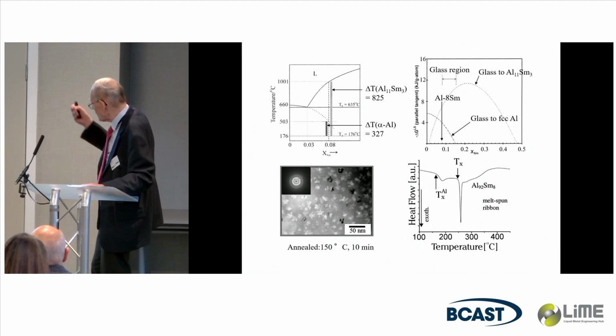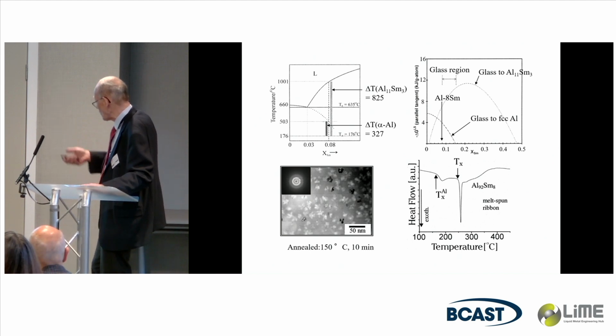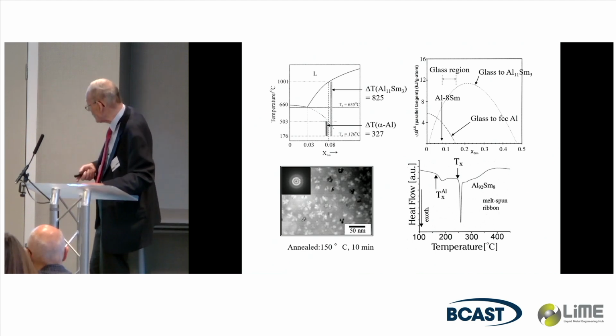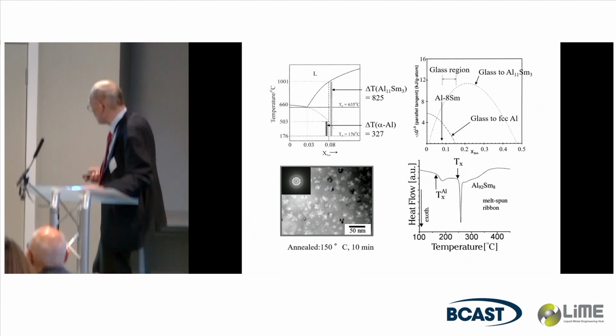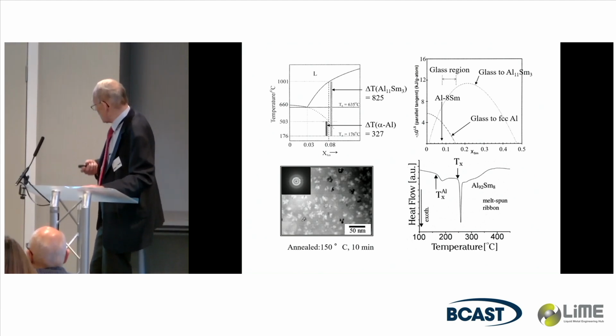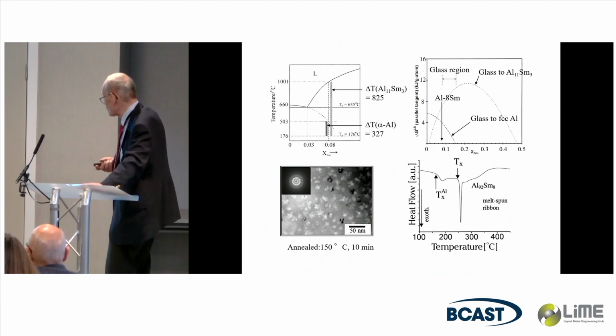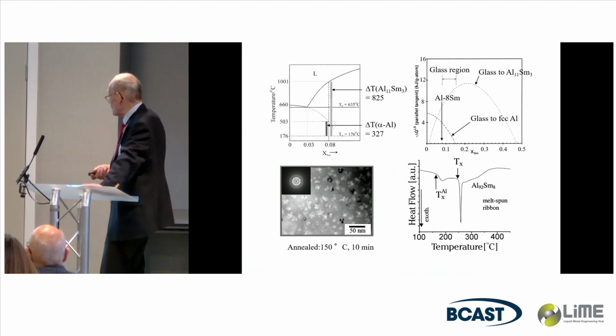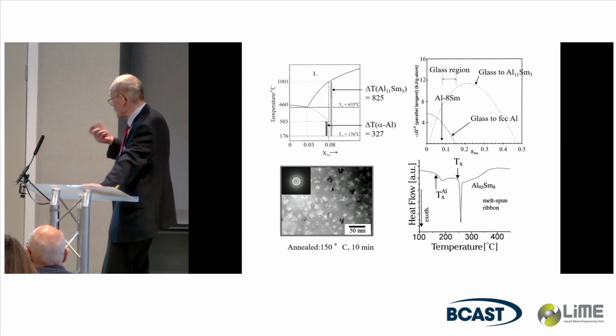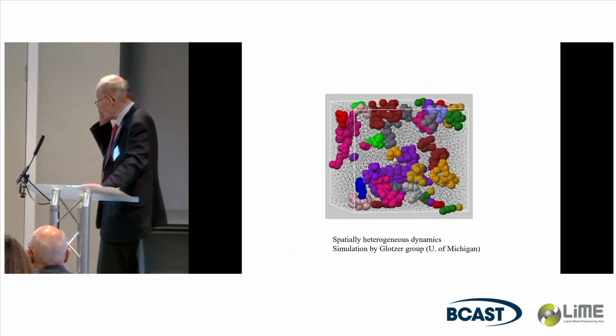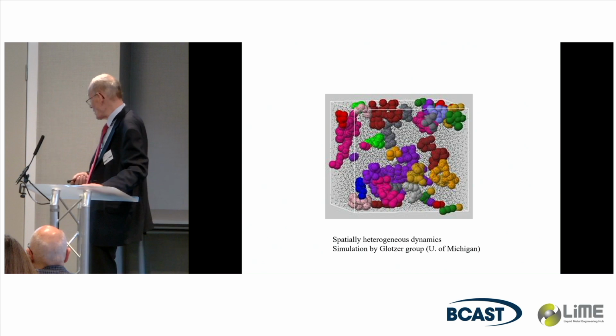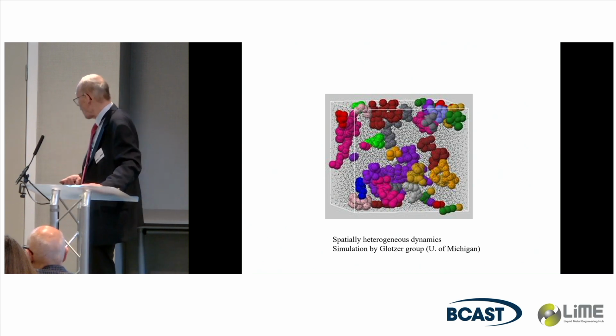And it clearly has to be heterogeneous nucleation because our compositions are hypereutectic, and you would expect some compound to form, like in aluminum samarium. And the driving force for formation of aluminum is half that for the intermetallic phase. So there has to be some heterogeneous nucleation site to promote the primary aluminum. And that turns out to be spatially heterogeneous groupings. And these are dynamic groupings.